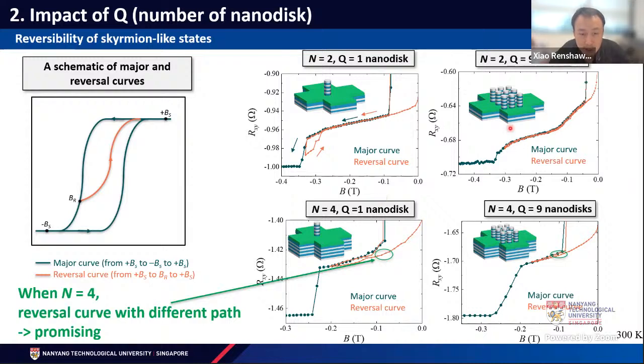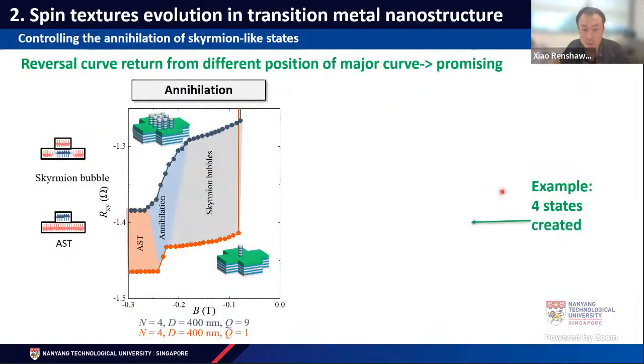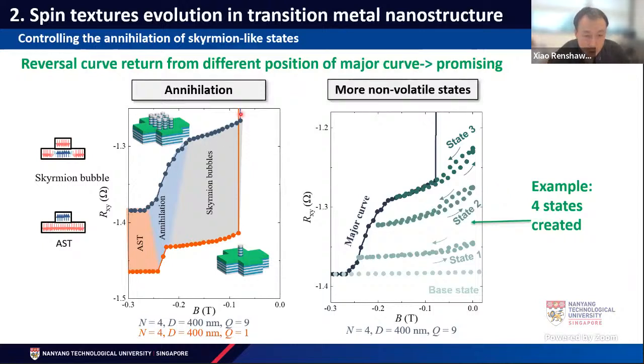When n equals 2, the whole reversal curve, or whole returning curve, follows exactly the green major curve. If we change to n equals 4, we start to see something. You see this returning orange curve is not perfectly matching the major green curve. So probably you can do something here to have multiple, let's say, skyrmion bubble states. And we identified that n equals 4 is a promising n number for us to get this. So then, of course, we play with it. First, on the major curve, we identify the skyrmion bubble region, and we just return from different places here, for example, on the right side. So following the dark green line here, this is our major curve.